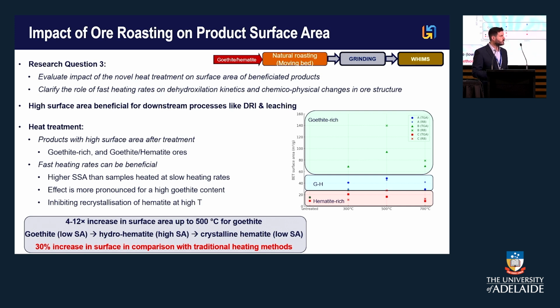And on average, fast heating makes a difference compared to slow heating rates. You see that, especially when goethite is in the mix, we can reach on average a 30% increase in the surface area against traditional heating methods.